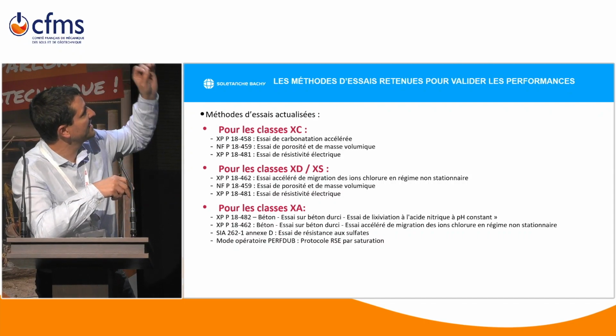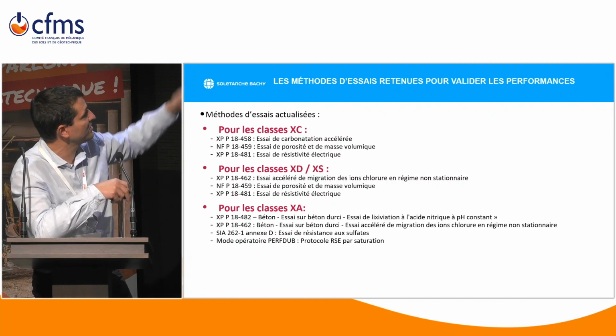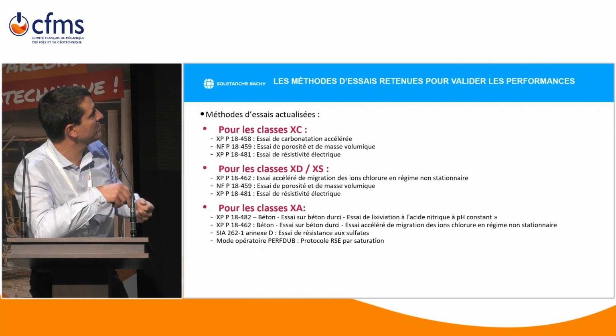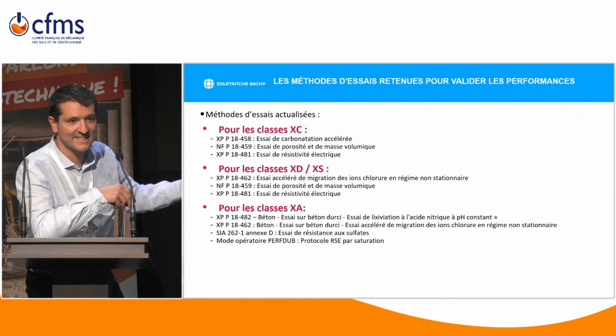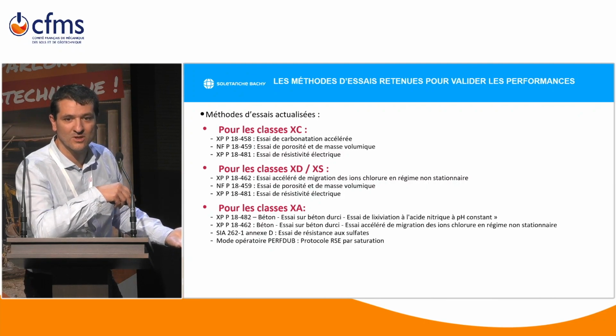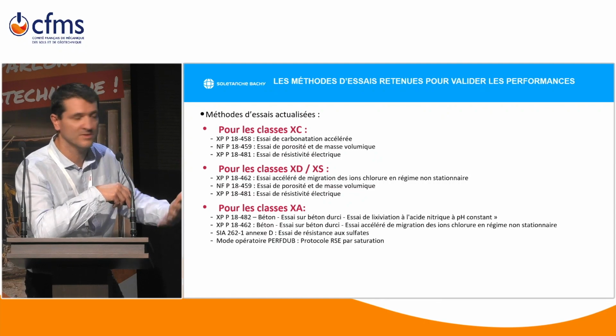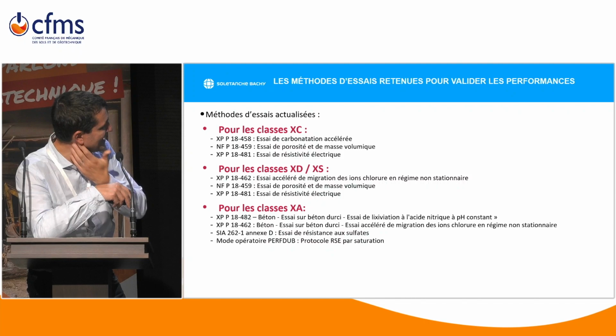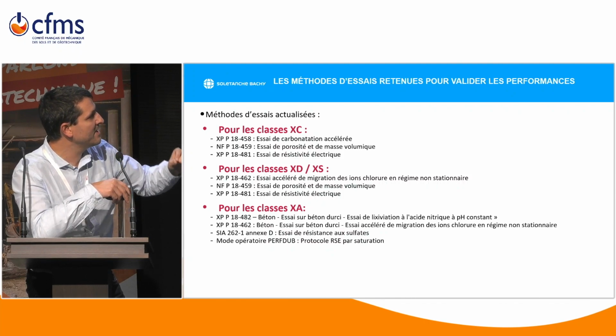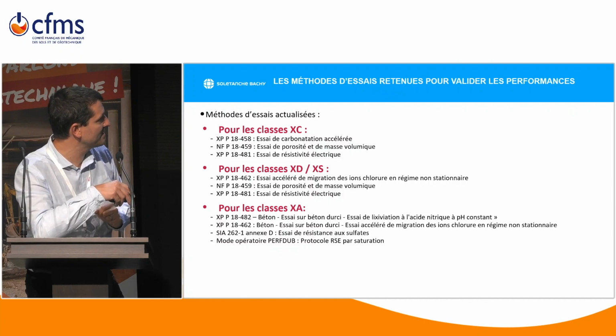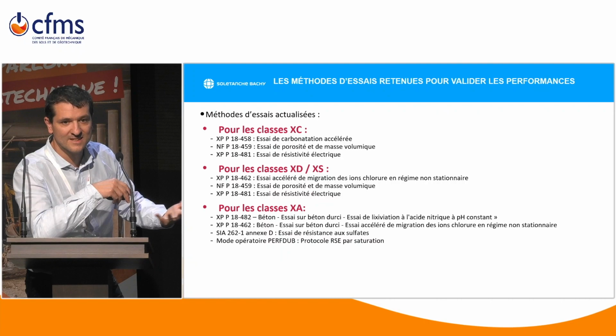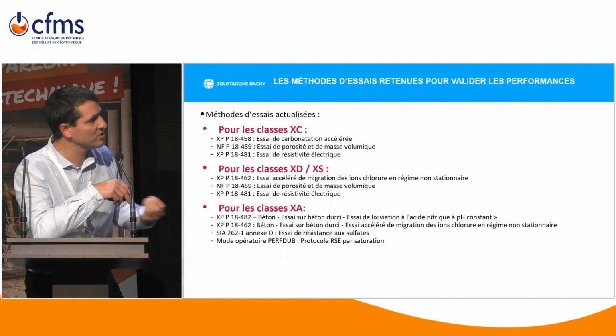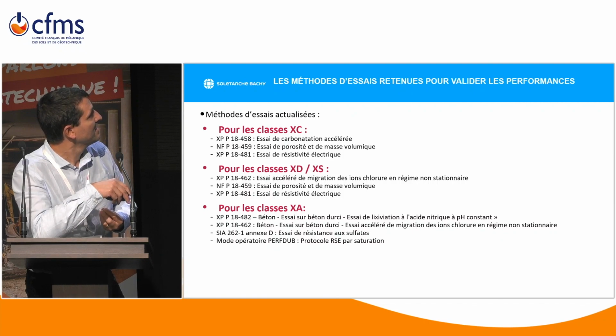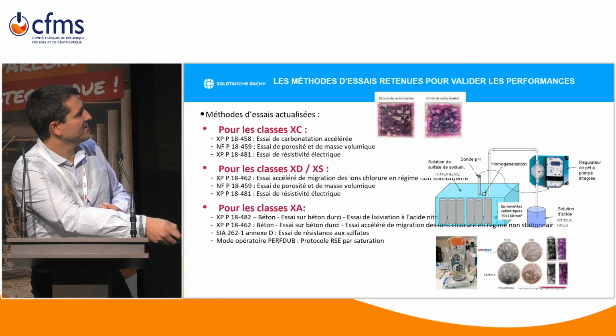that for each of the exposure classes that you are facing, you will have a dedicated test with a standard associated. For carbonation, we have accelerated carbonation, porosity, resistivity. For corrosion due to chloride, there is a chloride migration test. And even for chemical attack that we are always facing in geotechnical concrete, because we are in the soil and most of the time we can have sulfate from the soil or things like that, we have those tests to test the risk of low pH or the impact of sulfate in order to demonstrate that the alternative mix, which is, let's say, optimized from the prescriptive approach, will give you the right concrete for your project. Okay, so that's just to show how it works.